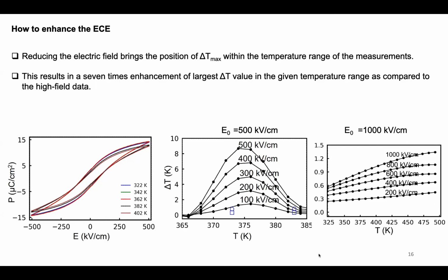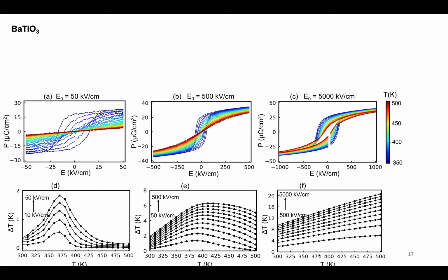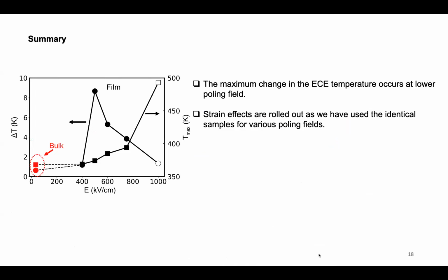So here I am only showing two fields, but we went up to different fields also. I show the final result, but just wanted to compare that with different concentrations. For that, we also did the BTO systems, and we got a similar result. This is from the simulations again. And the summary slide here tells that we applied different fields to the same samples. This is again the experimental data, I should say. So you can see the amplitudes are ranging from 400 to 1000, and for the different poling fields, we got different changes in the temperature, which confirms from the experiments themselves that the poling field plays a major role in determining the change in the temperature.